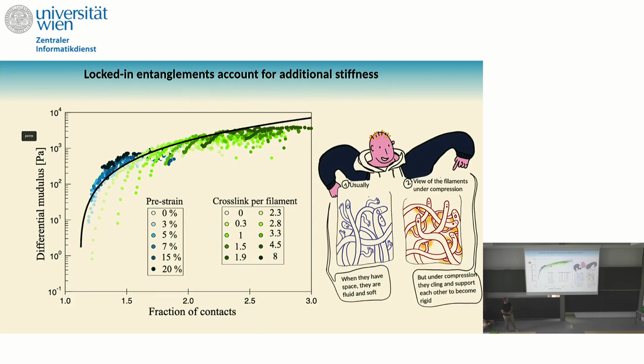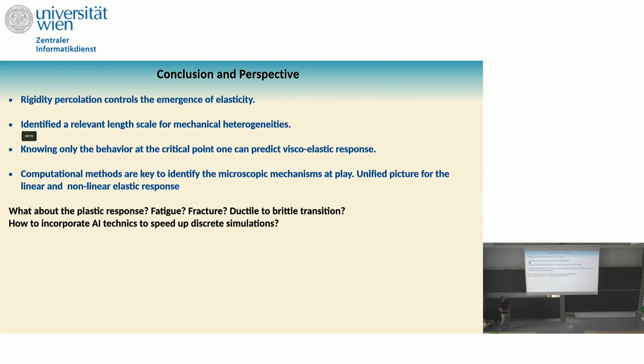So the take-home message from that is that when the filaments are in a good state, they have enough space, they are fluid, they don't need to interact with each other, they are at the edge of being solid. But then when you add compression on them, they need to support each other. The cell needs that a lot in order to push on obstacles. And this is by creating permanent contact by adding crosslinks, or non-permanent contact by just steric interaction between the filaments. Okay, let's go to the conclusion very fast, and perspective.